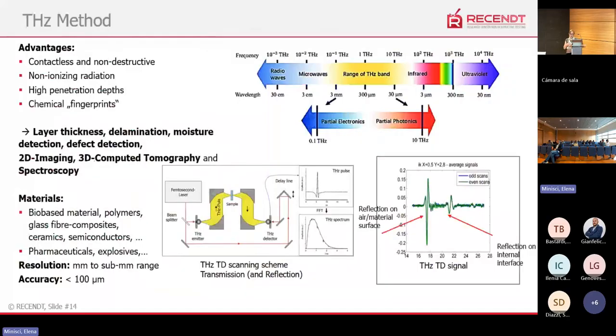But OCT has high resolution but a limited penetration depth, so we came to terahertz, which has the advantage of a higher penetration depth, with resolution from millimeters to submillimeters. Terahertz is in the range between microwaves and the infrared range, and is also an interferometric method where we can scan through the pulses. We can use it not only for spectroscopic measurements, but also to find layer thickness, delaminations, or in our case, moisture detection also. And we can also make 3D computer tomography with terahertz.